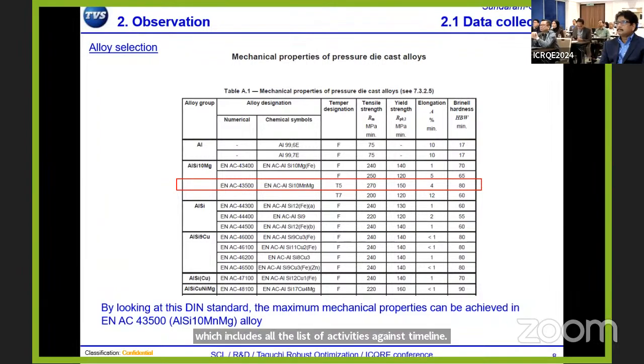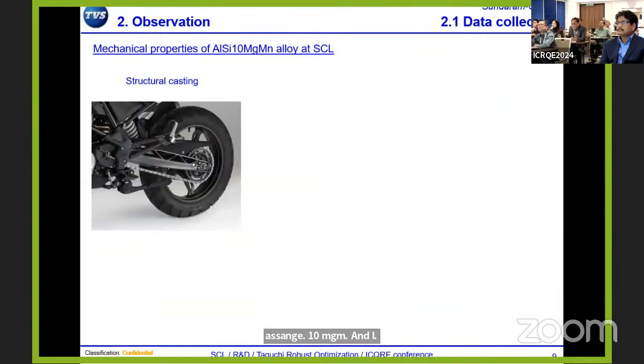So the next phase is the observation phase. Here alloy selection plays a major role. By looking at the DIN standard, the alloy is selected based on higher mechanical properties. The alloy selected is EN AC 43500, that is AlSi10MgMn alloy. At SCL, currently we are manufacturing a component, and you could see this is a structural member connecting between the wheel and the suspension. This component already uses this alloy, so we have taken this casting for our analysis.